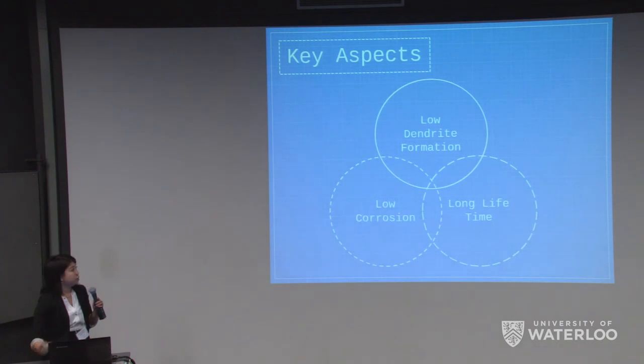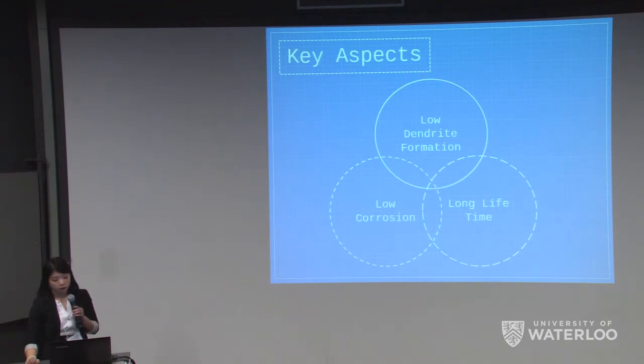In addition to the industry requirement of having the optimized gelling time, there were 3 other key aspects that we were taking into consideration, which would be low corrosion, low dendrite formation, and a long lifetime. Corrosion is an undesired side reaction during electrochemical reactions, which greatly reduces the performance of batteries. Corrosion can be described as an oxidation of the metal electrodes with the oxygen from various sources, such as moisture, water evaporation or decomposition, and hydrogen evolution.